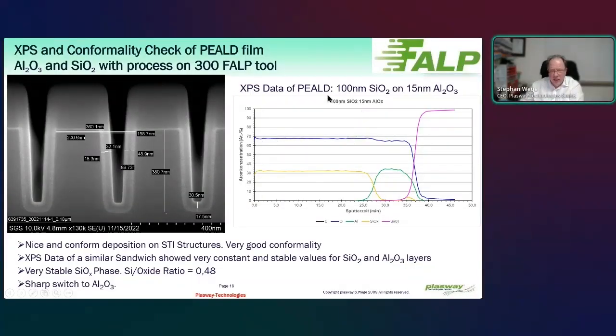This means over the complete 100 nanometer SiO2, we have a very, very nice and very independent stoichiometry. It just changes when you go into the aluminum oxide, and then you definitely have here also a flat aluminum oxide profile and a different oxygen profile, but it is also almost flat.